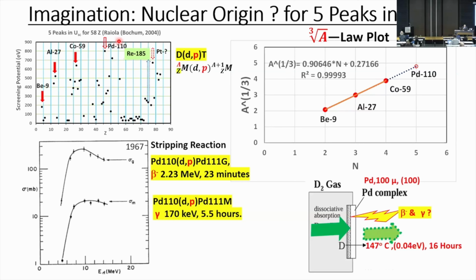It provides a chance to verify its nuclear origin because there are 6 stable isotopes in nature for palladium. Palladium-110 is only 12% of it. We may use enriched palladium-110 isotope as the screening material. It should produce many more protons to verify this nuclear origin. However, this enriched isotope is expensive. We may still use natural palladium as screening material and try to detect its products.